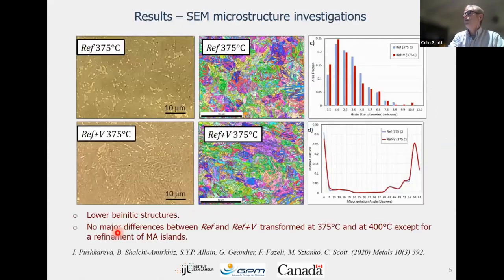So moving on. We did quite a lot of microstructural investigations on these steels, and I won't go into all the details of that. If you want, they've all been published. There's a Metals publication in 2020 that you can look at. When you do SEM, when you do EBSD, essentially you don't see any difference from the addition of the 0.2 vanadium. It's all lower bainite. You don't see any difference in the lath size or the effective grain size of the bainite, nothing at all. So you can't really see any major difference of vanadium in the optical or in the SEM microstructure.